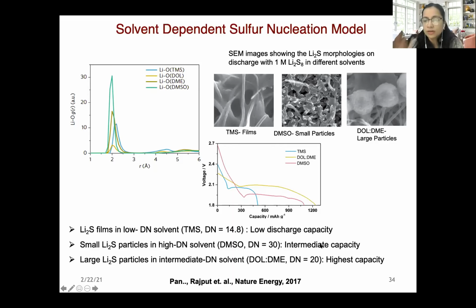But if you're on the other spectrum of the donor number, such as in case of DMSO, the solubility is too high. If the solubility is too high, your nucleation overpotential is also very high, which results in formation of these small particles, and it results in slightly higher discharge capacity, but still very limited.